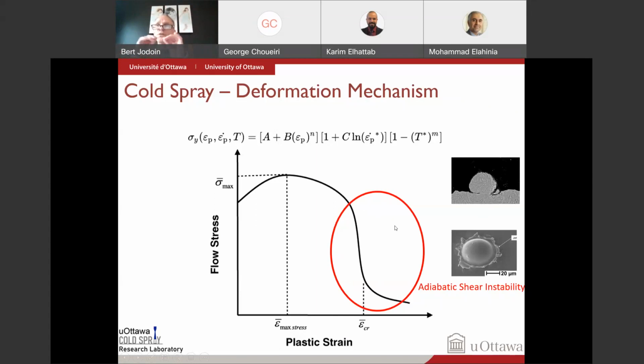We're talking about a few microns, a few nanometers, and that's why you get this sheath here that we call the jetting part. This material was locally at high temperature, not melting temperature, but high enough that basically your flow stress drops and it starts to flow almost like a liquid. So that's how the particles are deforming.